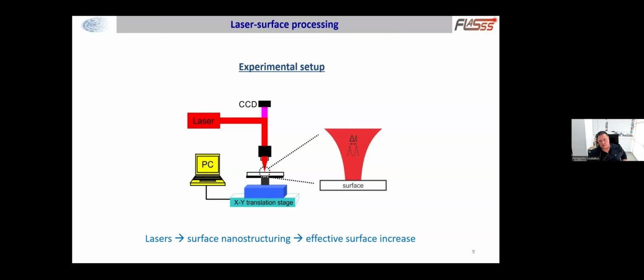So in our case, we employ a relatively simple experimental setup where we use a laser beam to focus on the electrode surface, the metallic surface. And using these lasers, we end up with surface nanostructuring, and essentially we end up with an effective surface increase.